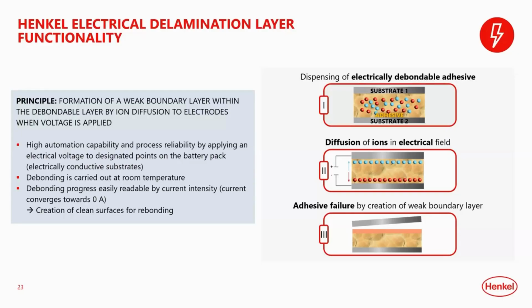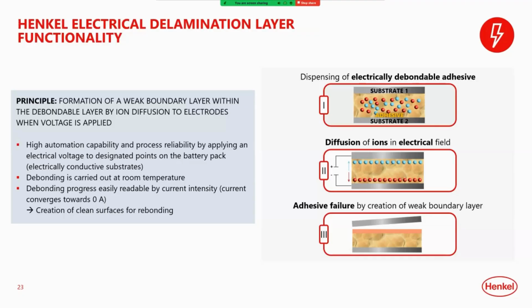Like in thermal delamination, the result is an easy to disassemble part, and the parameters such as voltage and time can be customized. So one interesting thing about this method is that you can basically measure or read the progress of the debonding as it's happening, because the current converges to 0 amps, indicating the completion of debonding. So then at that point, the material can be peeled off both substrates, leaving behind 2 clean surfaces.